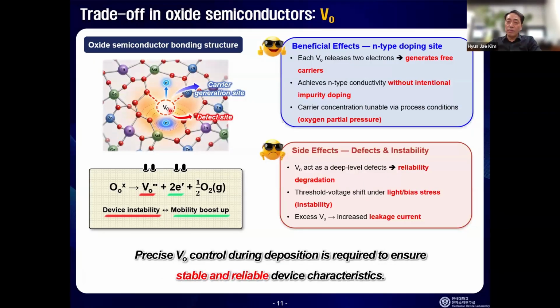Okay, but this is a trade-off. You need to have oxygen vacancy in order to have electrons. One more time, this is the defect, right? This is a multi-component system. If you don't have the oxygen, you could consider it a defect, right? So it has both. You have to have oxygen vacancy, but not too many. If too many, it's a defect and it's a cause of instability, right? This is a trade-off. But the keyword for oxide semiconductor is, yes, oxygen vacancy.